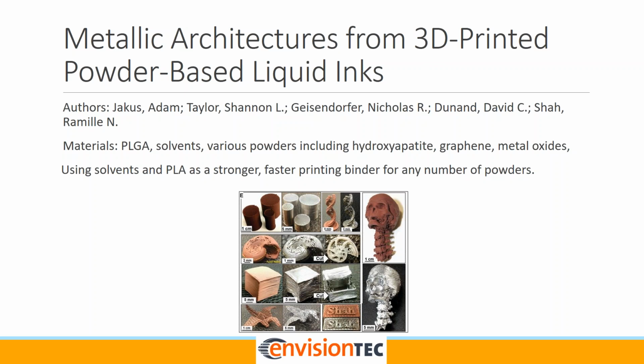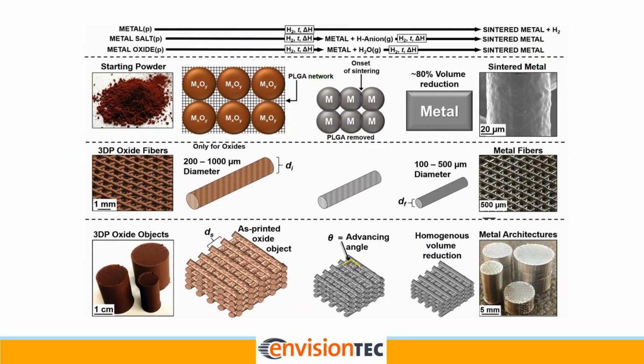On the left-hand side, you have the metal oxide powder. The addition of temperature with hydrogen causes the ceramic scaffold to reduce and shrink in size, and the non-metal portion of the ceramic construct goes away.